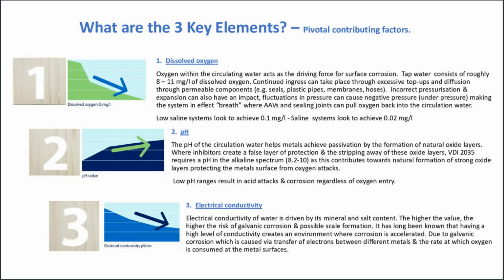So what are the three key elements? So dissolved oxygen. Oxygen within the circulated water acts as a driving force for surface corrosion. Tap water consists of roughly 8 to 11 milligrams per litre of dissolved oxygen. Continued ingress can take place through excessive top-ups and diffusion through permeable components. Examples are seals, plastic pipes, membranes and hoses. Incorrect pressurization and expansion can also have an impact.